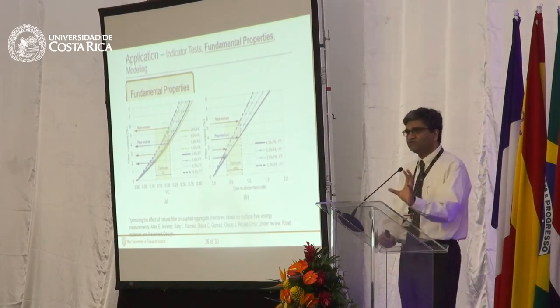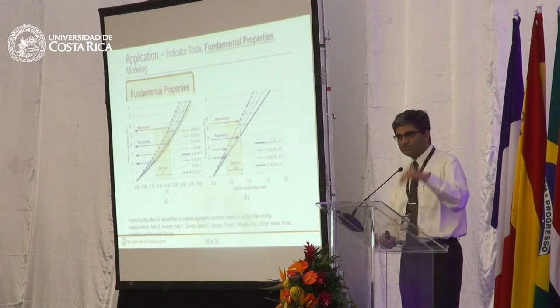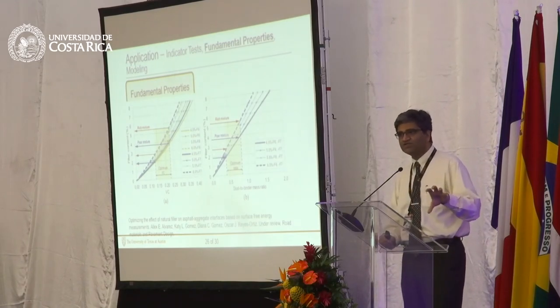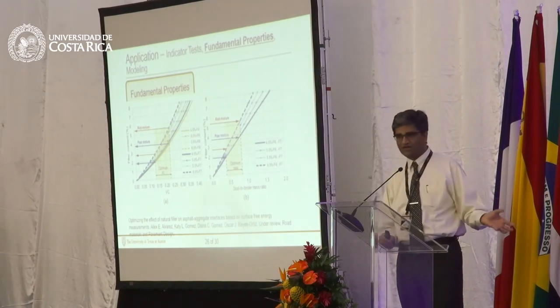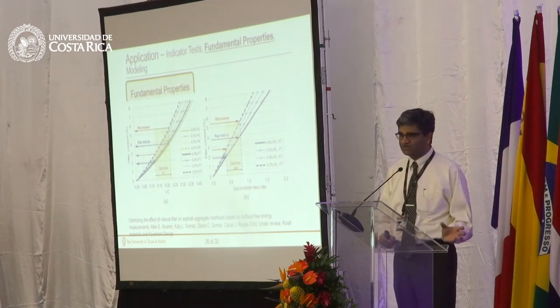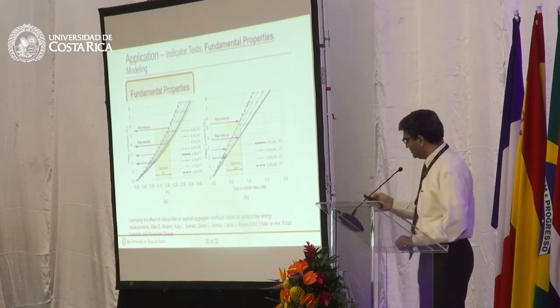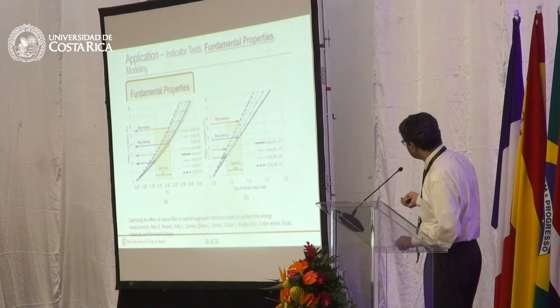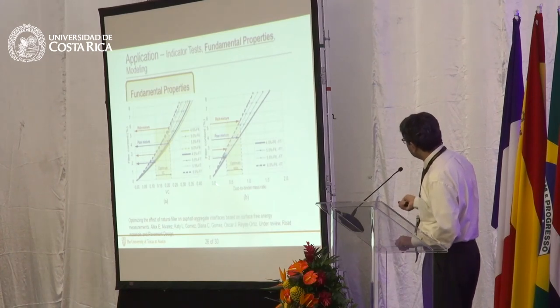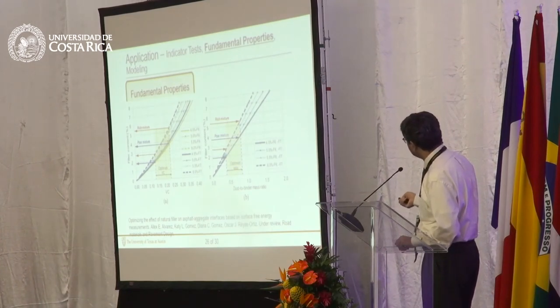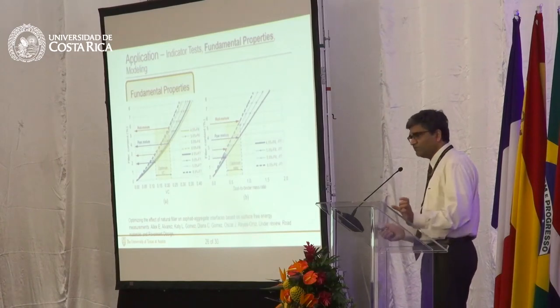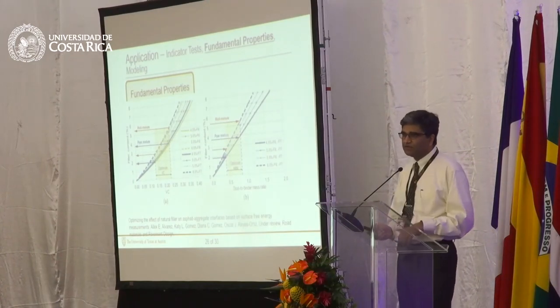If he had too much fines in there, the surface energy would drop to a point where it was not good in adhesion. If he had too little, the surface energy was again indicating that you did not have a good adhesion. There was really an optimum range that he found from this study, which shows the dust to binder ratio versus filler concentration. And these bars basically show you what is a good optimum window. It's a very interesting paper.